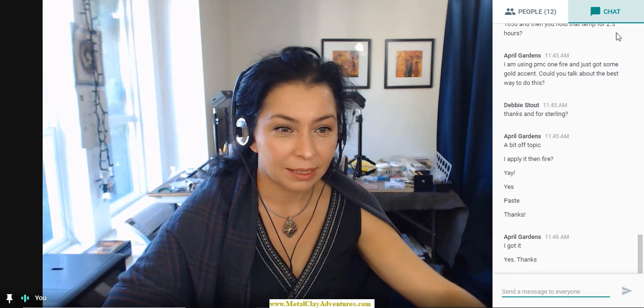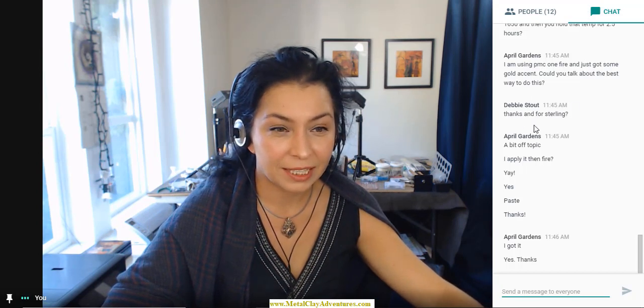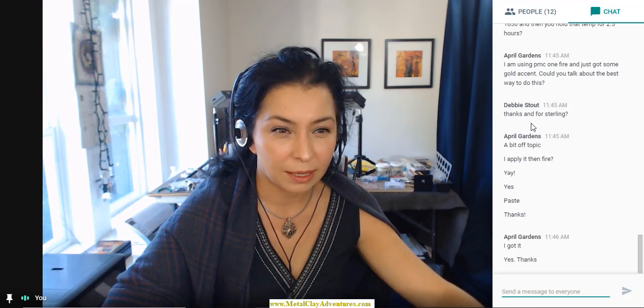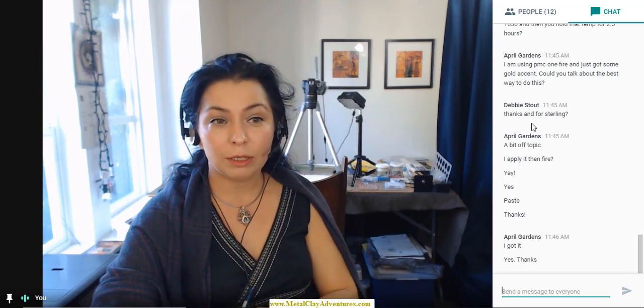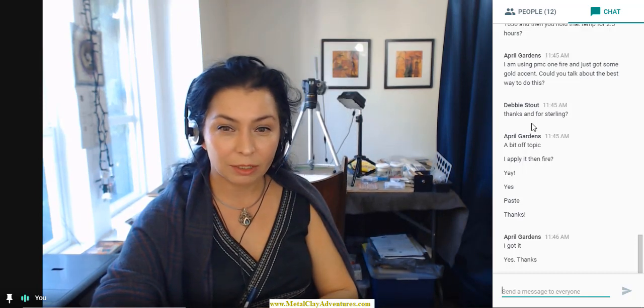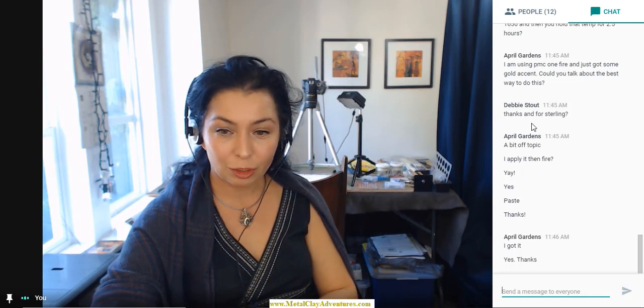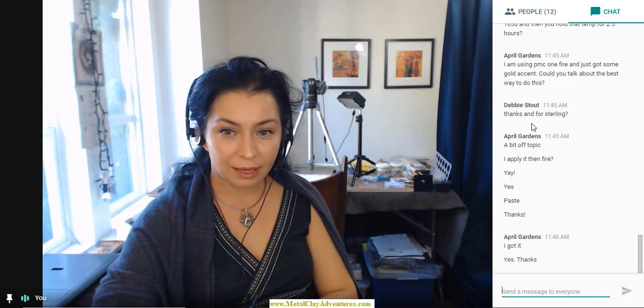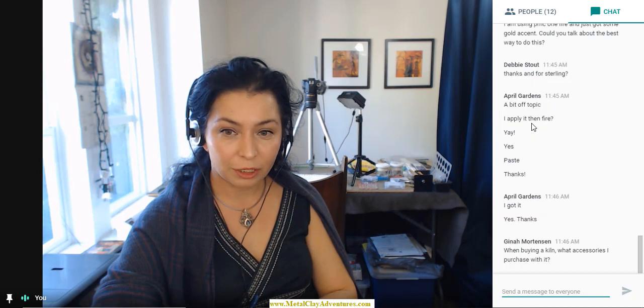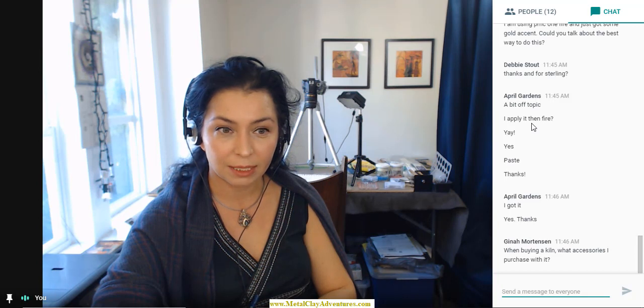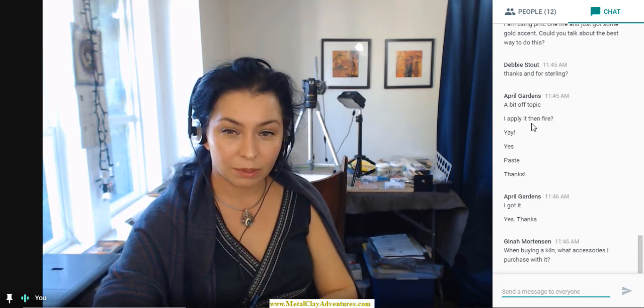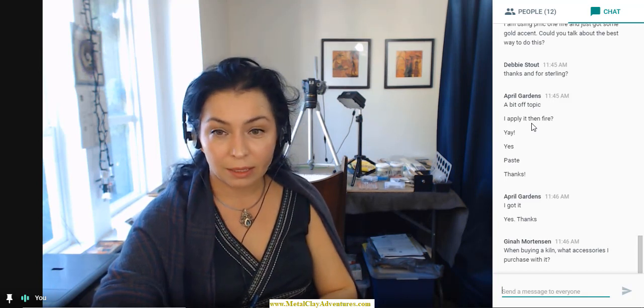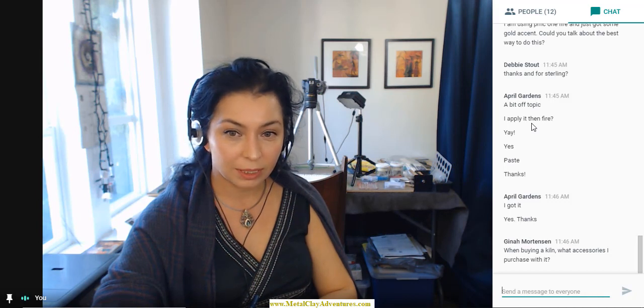DB is asking the temperature and holding time for sterling. DB, it usually depends on the brand you are using, but usually the perfect temperature for sterling is 1600. It's just about 50 degrees less than for fine silver, and the holding time is 2 hours.